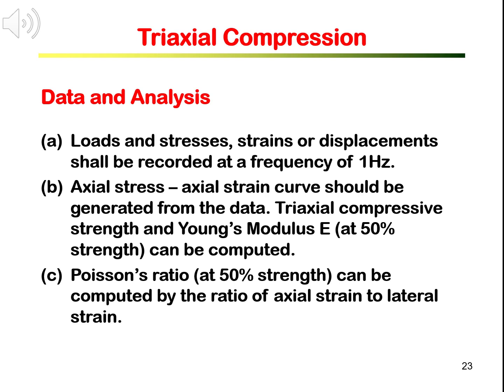Together with the axial stress, axial strain curve, you can calculate the Poisson's ratio as a ratio of the tangent of the axial strain curve to the lateral strain curve. It is recommended to calculate the Young's modulus and the Poisson ratio at 50% of the peak strength.